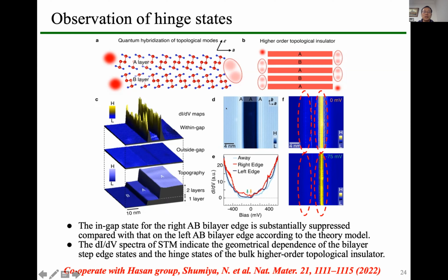We find some positions like this. There is a change here. So this side is a bilayer step edge, and this side is also a bilayer step edge. But the structure is just like this or that. So we measured the dI/dV spectra at these two positions, and we found that only at this position we have a very strong density of states. This side we don't have a very strong density of states. So this means that this is really a higher order TI.